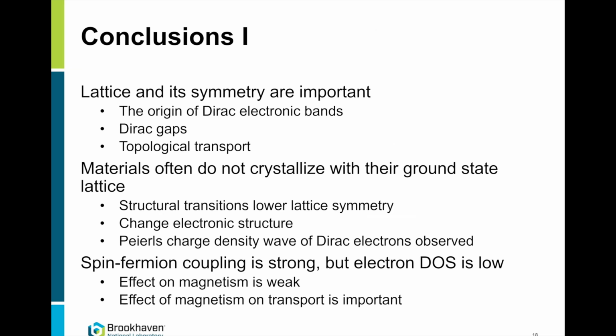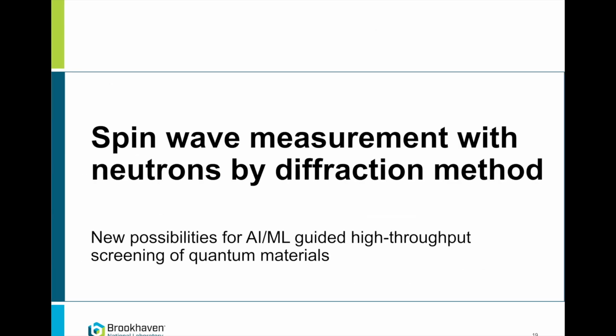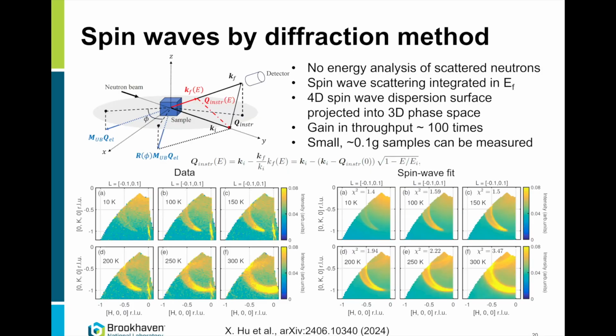So we observed the Peierls charge density wave, and the spin fermion coupling from the spin wave damping is weak. But the coupling constant itself is strong, so the effect of magnetism on the conduction electrons would be strong if we would be able to find a material with this weak ferromagnetism. Okay, we were stuck by trying to measure spin waves on these small samples. We decided to measure diffraction and to just study magnetic structure. And surprisingly, we were able to measure spin waves on a diffractometer.